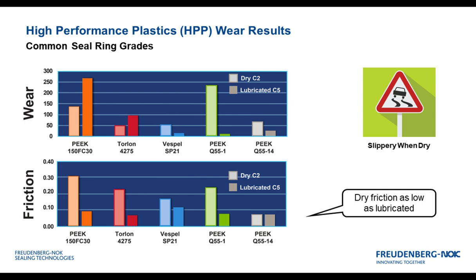What you're seeing now is a graph of some of the test results we've gotten. The top graph is wear. This is a wear factor for measuring how much wear occurred. There are 2 conditions here, the dry condition in the lighter color, and then the more darker color would be the lubricated condition at C2 versus C5. The materials, the orange, the red, and the blue material are some common materials used today in the industry for high-performance plastics, a PEEK, a Torlon, and a Vespel grade. The last 2 materials are PEEK grades used by Freudenberg.